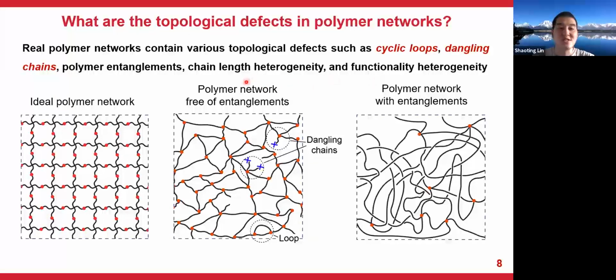So here the chain length is defined as the number of monomers between the neighboring cross-linkers. And the functionality is defined as the number of chains connected to one cross-linker. And if one end of the chain becomes inactive, it basically introduces one dangling chain. And the number of the inactive chains connected to one cross-linker defines the order of the dangling chains. So for example, we term this one as the first order dangling chain. And we term this defect as the second order dangling chain.